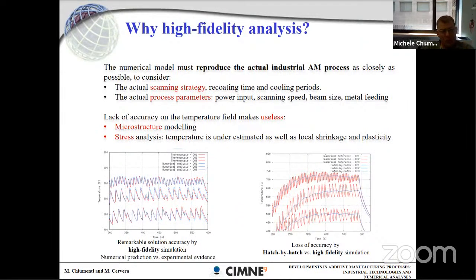One is the cooling rate, as you said, first during the activation. So you need to reach the peak temperature, but then the final cooling rate, because once you go through the alpha beta range, this cooling rate will define the final microstructure in terms of alpha phase, beta phase, or martensitic phase. So according to this speed, this rate, you have one microstructure or another. So you need the accurate definition of cooling rate.